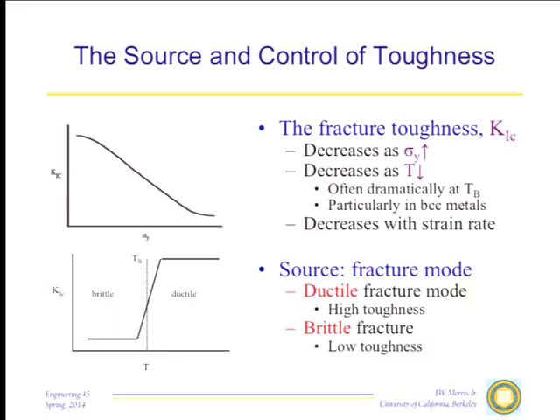Here in Richmond, in the Second World War, it turned out the ship plate that they were using was being tested in Richmond at normal temperatures, like outside, 60 degrees or so. The ductile-brittle transition of that steel was about 50 degrees Fahrenheit. So they were testing it right here. They would then put it in the ocean, right here. And problems ensued. And the recognition of the ductile-brittle transition was the other piece of the puzzle.